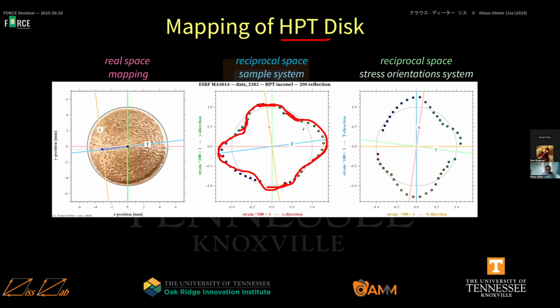What we do is we strain in the HPT, then the lattice planes, they yield, or they should according to the Schmid factors, and when we release, we get more relaxation in some direction and less relaxation in other directions. That's, well, roughly spoken, that's how we get this butterfly. So we can plot this as a function of x and y, the same x and y here. So this is the orientations now.